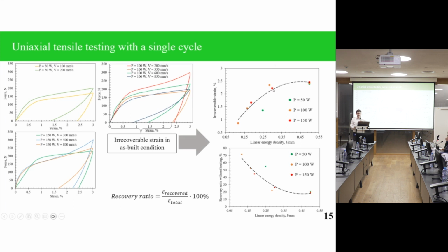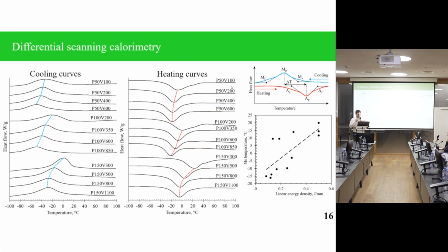That means that for these samples, we do not have any recovered deformation because of the transformation, and all deformation here was recovered only by pure elasticity. And these results are explained by differential scanning calorimetry.